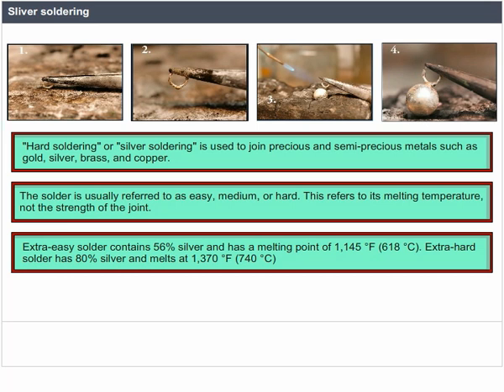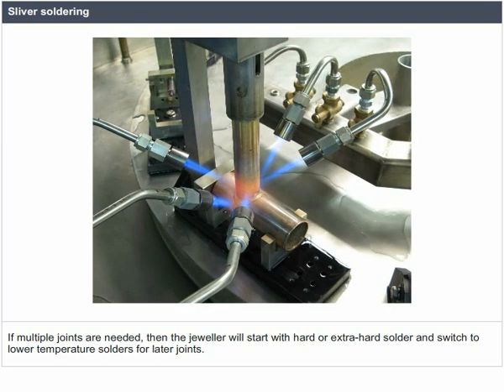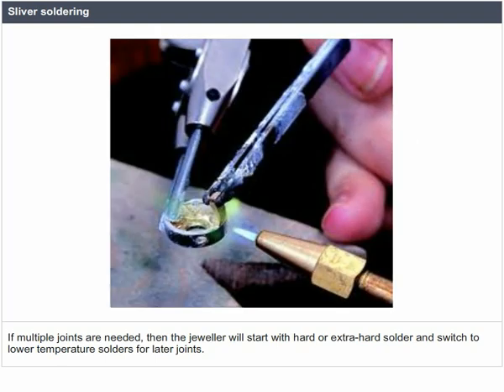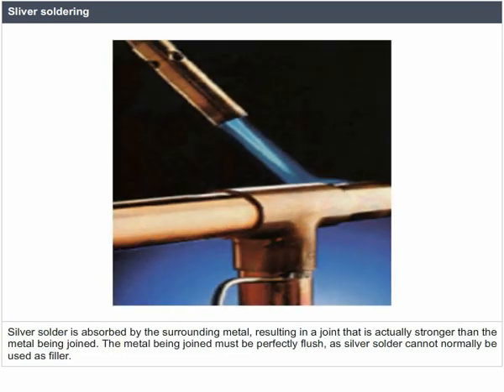If multiple joints are needed, then the jeweler will start with hard or extra hard solder and switch to lower temperature solders for later joints. Silver solder is absorbed by the surrounding metal, resulting in a joint that is actually stronger than the metal being joined. The metal being joined must be perfectly flush, as silver solder cannot normally be used as filler.